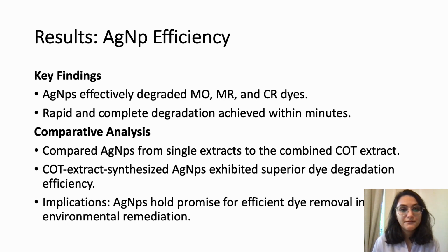Now let's dive into the key findings of the study regarding the effectiveness of silver nanoparticles in dye degradation. The study demonstrated that silver nanoparticles effectively degraded the selected dyes of methyl orange, MO, methyl red, MR, and Congo red, which is CR. Notably, this degradation was rapid and complete, achieved within a matter of minutes. In a comparative analysis, the study examined silver nanoparticles synthesized from single extracts and those synthesized using the combined COT extract. The results showed that silver nanoparticles derived from the combined COT extract exhibited superior efficiency in dye degradation. These findings have significant implications, indicating that silver nanoparticles hold promise as a highly efficient method for removing dyes in environmental remediation.